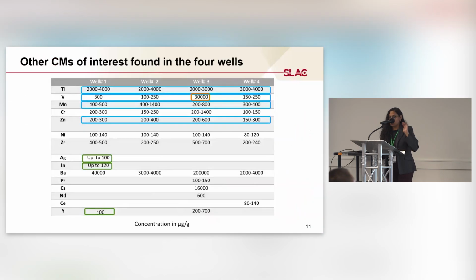So this is a table summarizing different critical minerals that we saw in all 4 different wells. Titanium we saw in a few thousand ppm, vanadium in a few hundred ppm, and in one well, well number 3, you can see in the red highlighted box that it was present in about 30,000 ppm, which is weight percentage level. And zinc was present in 100 to 600 ppm, and in one particular well, only in one unit. It was not throughout the well. It was only just one section. We saw a few, like 100 ppm level of silver, indium, and yttrium as well. And all the concentrations are in ppm here.